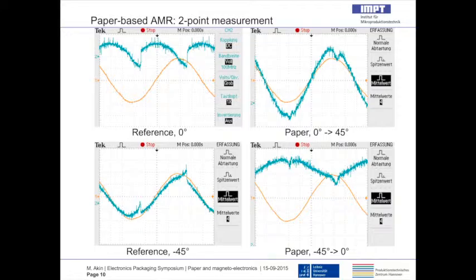What happens on paper? On paper, we obtain a response that's here overlapped on the blue curve with a sine that's coming from the induced voltage of the contacts and so on. But this is the response you would get when having a 45-degree angle between electric current and magnetic force on a smooth surface. So here again, we have obtained that shift in electrical resistance. On the reference substrate, when we have a minus 45-degree angle between the electric current and the magnetic force, we measure the following response that's overlapped with the sine curve that's induced voltage from the contacts and the wiring. But this is something that we know.